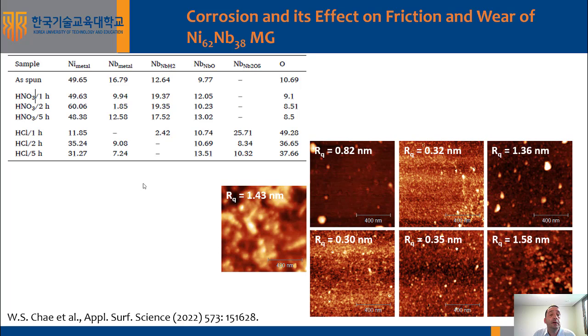The surface compositions were then measured by XPS, and depending on the type of acidic solution, we find very different oxide formations. After immersion in hydrochloric acid, the main constituent of the surface is niobium pentoxide, with no nickel oxide contribution, while after nitric acid exposure we rather have a niobium oxide present at the surface.